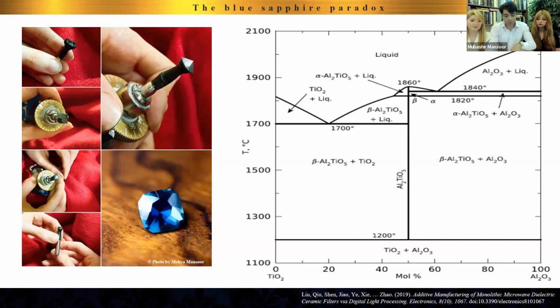And a great deal of gemological literature has used this diagram to explain the heat treatments in blue sapphire, which is not correct. Because, as we will show very shortly, in order to explain the heat treatments of blue sapphire, one should remember something, and you have probably heard of it, it's so common knowledge. Heat treatments of blue sapphire take place in reducing environments. What does that mean? Reducing environments mean we have very little oxygen in the furnace when we are doing heat treatments of blue sapphire. So that is known from an experimental perspective. People who are doing these treatments know it very well, that they have to reduce the oxygen in the furnace in order to be able to create these beautiful blue colors.